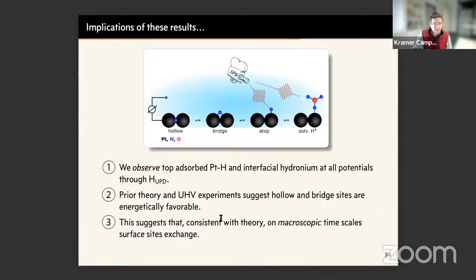Okay, so this point one just summarizes what I just told you. We observe atop adsorbed species and perhaps this interfacial hydronium at all potentials through UPD. In UHV, it is clear that hollow and perhaps bridge sites are energetically favorable. This is also what most theory tells us. I would suggest that we can reconcile 1 and 2 by suggesting that on macroscopic timescales, at least, there is exchange of this atop adsorbed and other types of adsorbed hydrogen. We are building an experiment now to probe this hollow site adsorbed species.